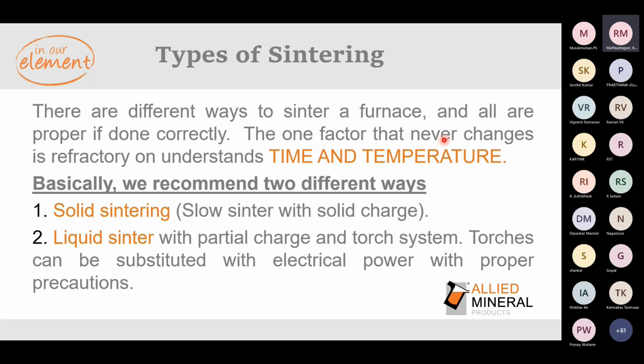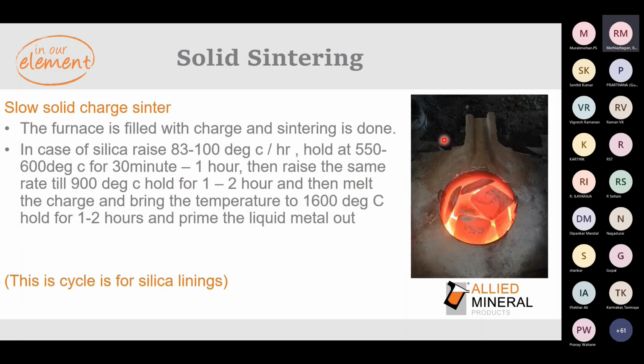So when it comes to types of sintering, there are two types: solid sintering and liquid sintering. If you talk about solid sintering, everyone does the same operation: the furnace is charged with scrap and the sintering is done through the power. Our recommendation is to rise between 80 to 100 degrees Celsius per hour, depending upon the furnace size. Hold at 550 degrees Celsius for 30 minutes, then rise to 900 degrees Celsius and hold for 1 hour. Then you can increase the power, melt the scrap, and take it to about 50 degrees Celsius above your tap temperature, which is normally between 1550 to 1600 degrees Celsius, and hold there for 1 to 2 hours, depending upon the size of the furnace.